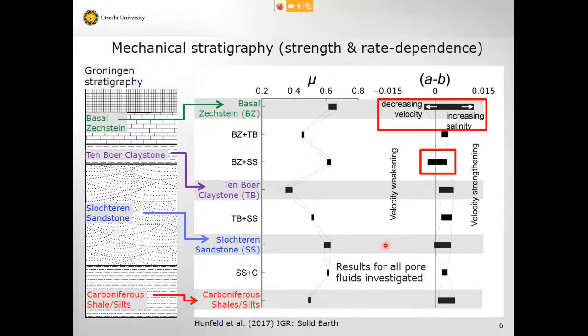Interestingly, all of these simulated fault rocks have got A minus B, this measure of potential for accelerating slip, all positive, except this basal Zechstein material at very low velocities and mixtures of this basal Zechstein, this carbonate anhydrite evaporite rock, with the sandstone. Here it is. That gives you accelerating slip. So these are potentially, from the point of view of a rate and state friction model, potentially seismogenic materials, more so than the rest.